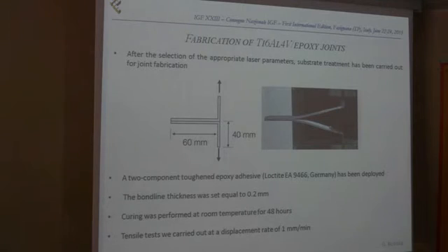So we decided to bond the samples using 350 millimeters per second and 1,250 millimeters per second, also because it would have been more appealing from a production rate point of view than 50 millimeters per second. And we changed the two levels of fluence. So we did 20 joules per square centimeter and 50. The bond line thickness was set equal to 0.2 millimeters, and we bonded the samples together after the treatment, and we debonded the samples by applying a peel load.